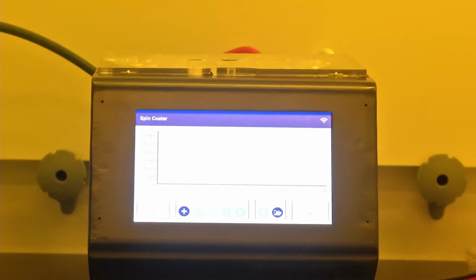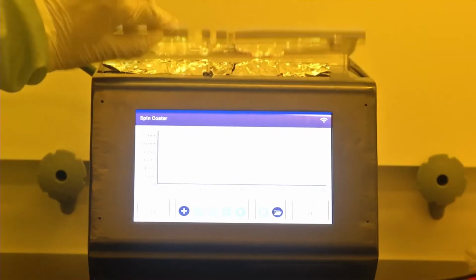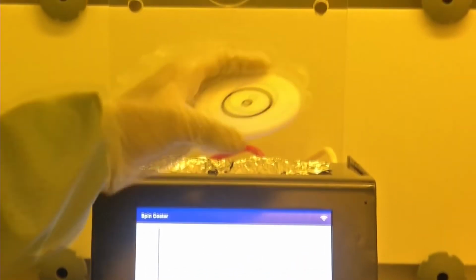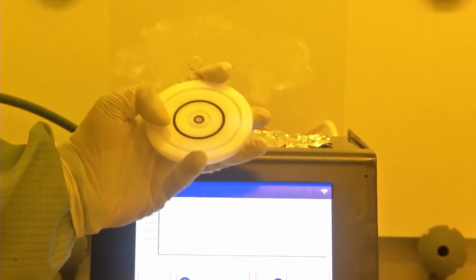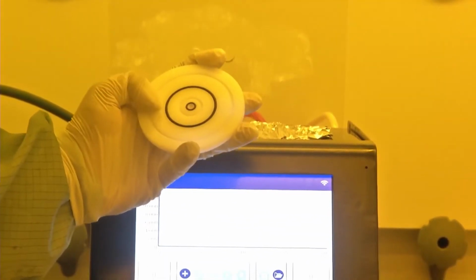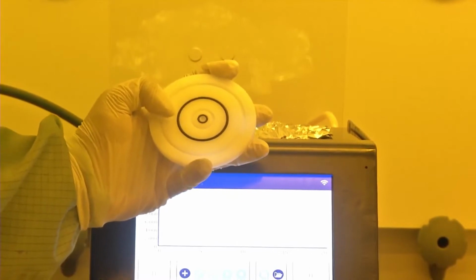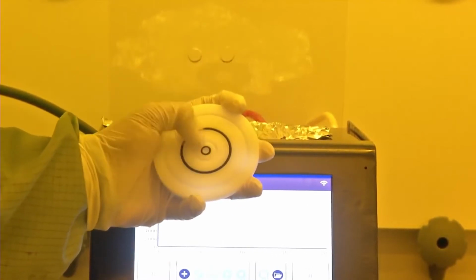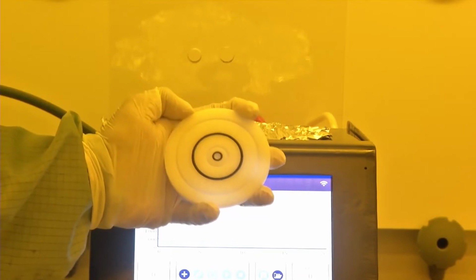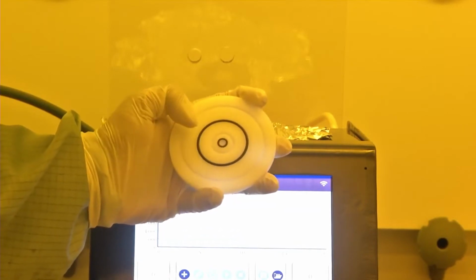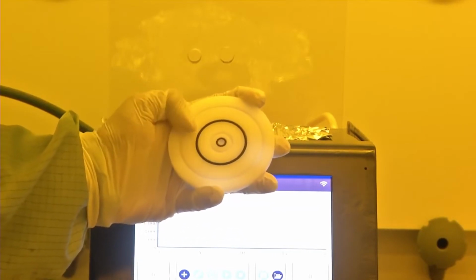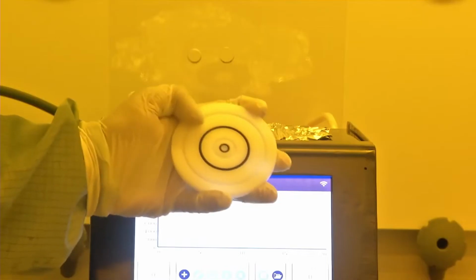So now we will see what a substrate holder looks like. We can open the lid of the spin coater and then take out the substrate holder. So this is how a substrate holder looks like. The black ring that you see is the O-ring. There are multiple grooves depending upon the size of the substrate. The smallest one can be for small wafer pieces, the middle one can be for a 3-inch silicon wafer, and the larger one can be for a 4-inch silicon wafer.